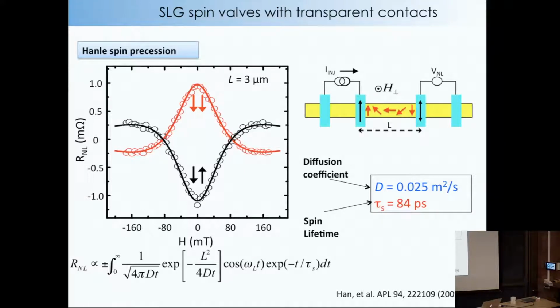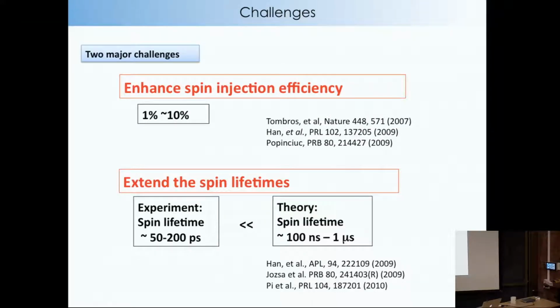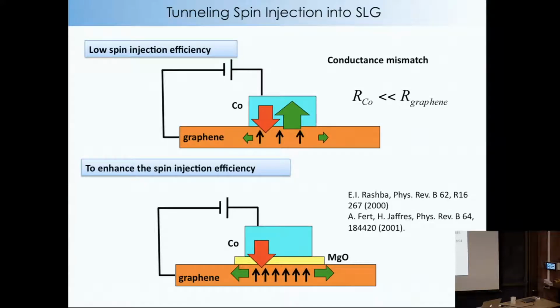But so what's causing all these problems? Okay, so when we were early in the field, we noticed that the injection efficiencies were pretty low, and the lifetimes were very low. So this was some issue. And so the question is, what's going on? And even now, the question is still, what's going on? And so one of the big problems that comes about is this thing called the conductance mismatch. And it sort of works like this in a cartoon picture. So what happens is I have a metal contact, and I have graphene. Now graphene is a pretty good conductor, but it's not quite metallic conductivities.